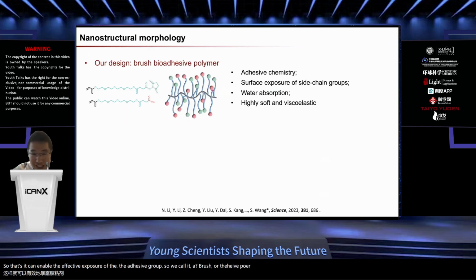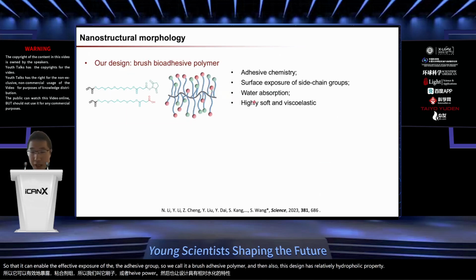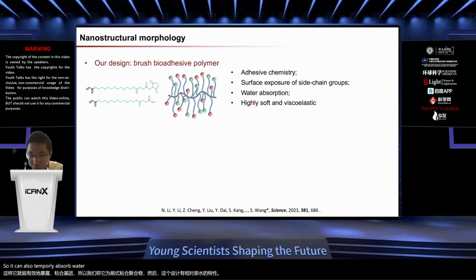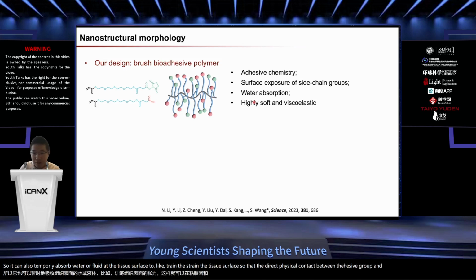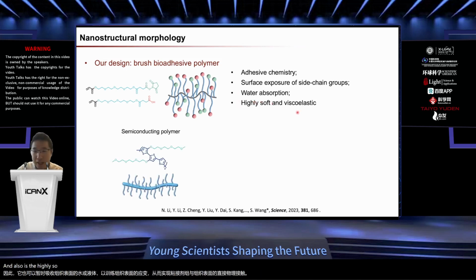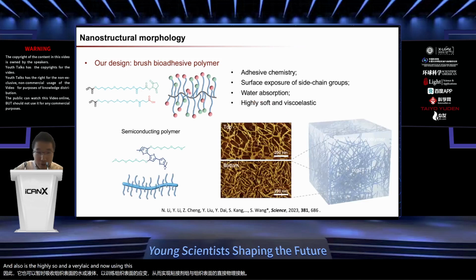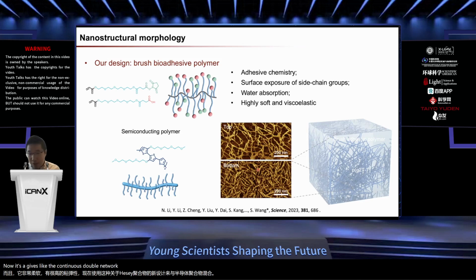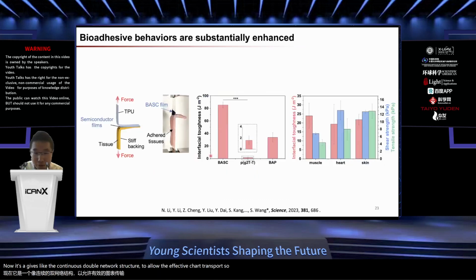This design also has relatively hydrophilic property, so it can temporarily absorb water or fluid at the tissue surface to drain the tissue surface so that direct physical contact between the adhesive group and the tissue surface can be realized. And it is also highly soft and viscoelastic. Now using this new design of a bioadhesive polymer to mix with a semiconducting polymer gives a continuous double network structure to allow effective charge transport. So using this design, the adhesive property can be kept at a similar level to the bioadhesive polymer and significantly improved compared to the semiconducting polymer by itself.